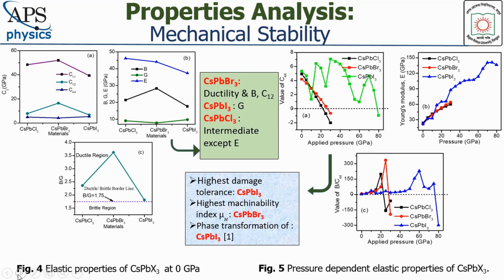The zigzag curve of C44 gives the information about pressure dependent phase transition of cesium lead iodide. It has highest damage tolerance, but the highest machinability index is observed for cesium lead bromide.